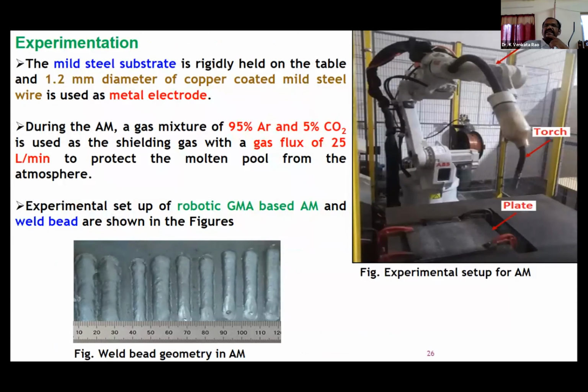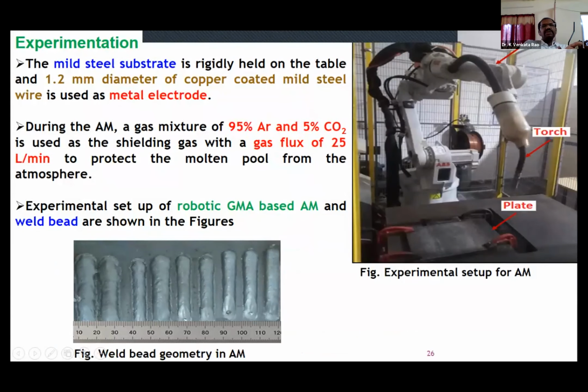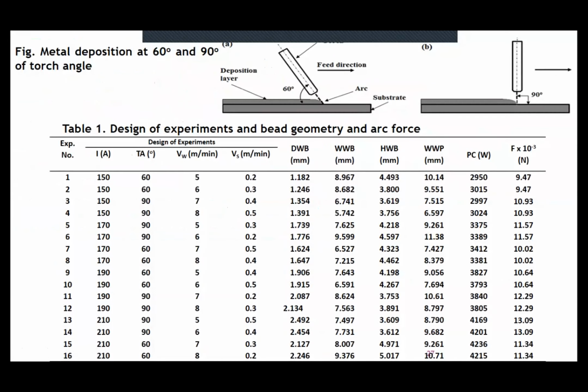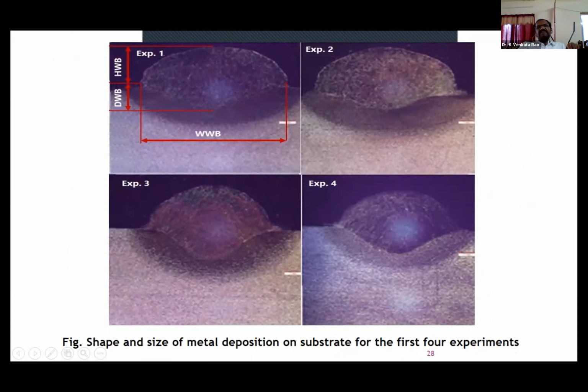This is the experimental setup. The robot costs around 38 lakhs. We purchased it. We carried out experiments as per design of experiment, that is orthogonal array L16, and in each experiment we measured depth of weld bed, width of weld bed, height of weld bed, width of weld pool, power consumption, and arc force. So here our aim is that width of weld pool is to be reduced, according to our requirements.